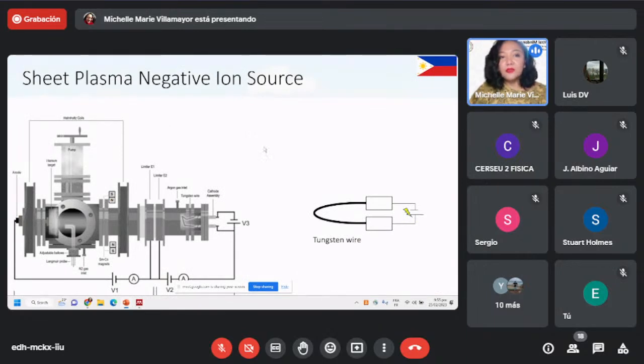I would also like to introduce to you the sheet plasma negative ion source. So in the previous example, we used the magnetron sputtering technique, whereas here we use something called thermionic emission to create the sheet plasma negative ion source. So what does that mean? In this chamber, we actually have two parts. We have the plasma production chamber here, and then towards here is the plasma extraction chamber. So we create plasma at the production chamber, and then using a series of electrical wires and magnetic field, we can actually guide the plasma from the production region towards the extraction region.